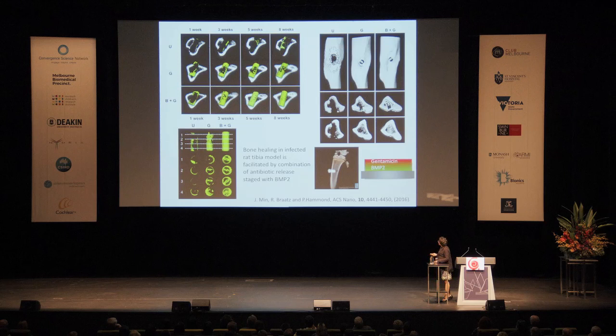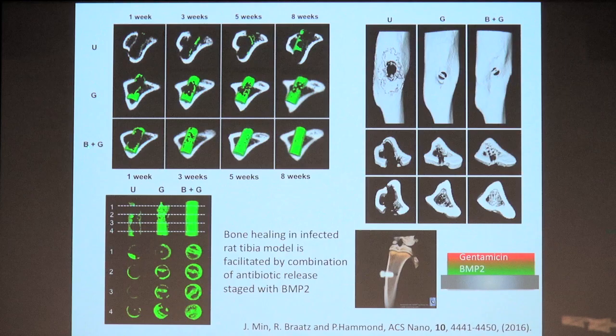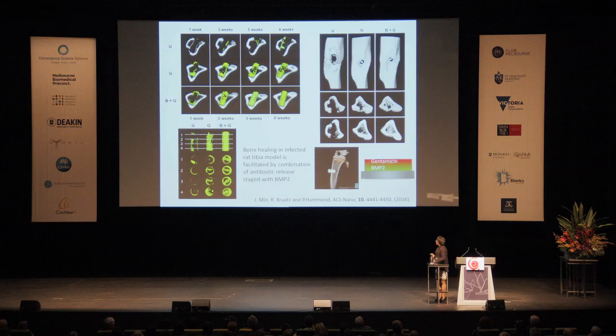So it turns out that with the combination of BMP2 and gentamicin sulfate together, we can actually regenerate the bone much more rapidly. By 5 to 6 weeks, we have a full coating of bone. It's integrated throughout the implant. And here we can see, these are just simply different angles of the micro CT, that in the case of the combination, we get a very nice regeneration of bone for this implant.